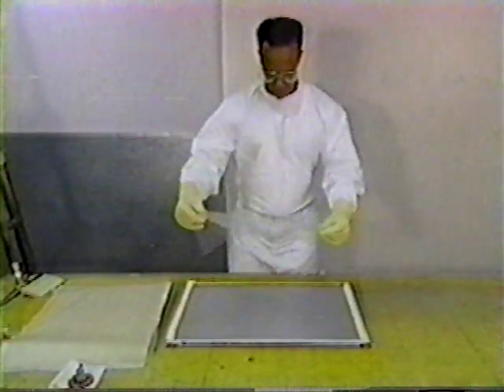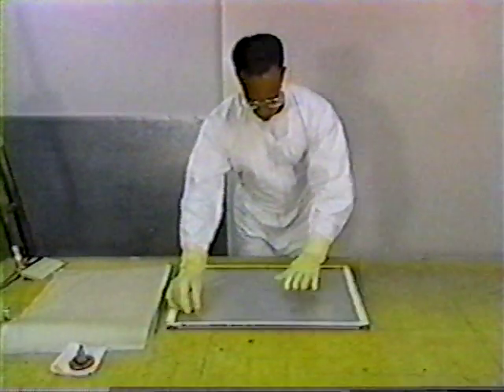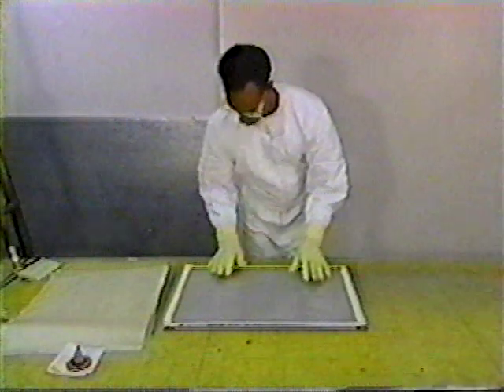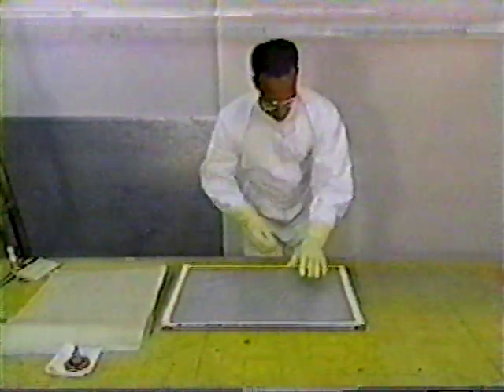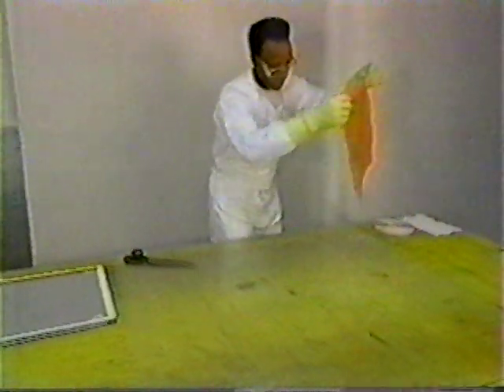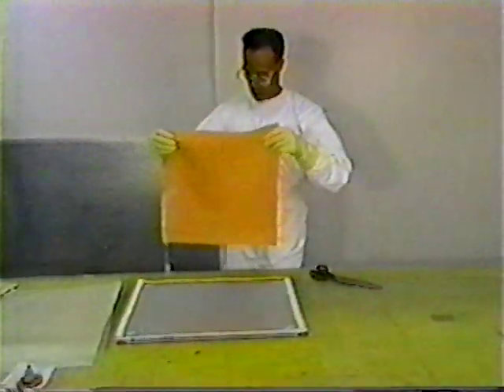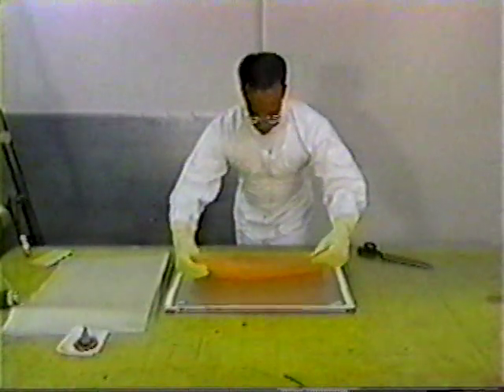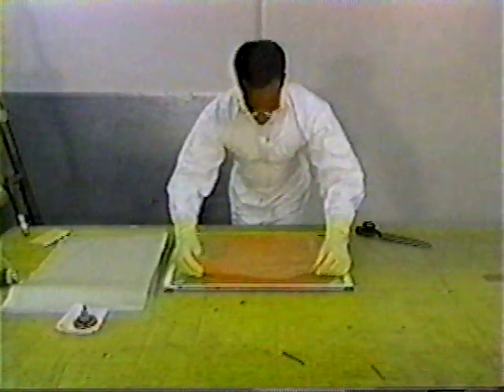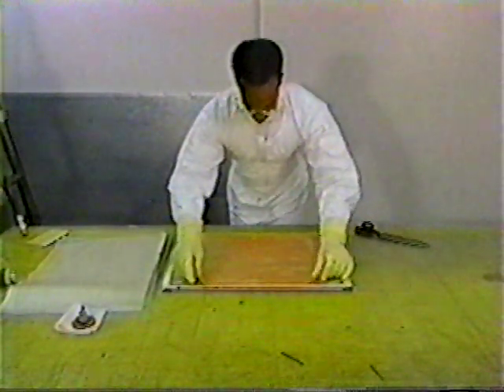Place a sheet of non-porous parting film on a surface that can withstand temperatures greater than 200 degrees Fahrenheit. Next, turn the ply stack over so the fiberglass material faces upward, and position the stack at the center of the sheet of non-porous parting film.